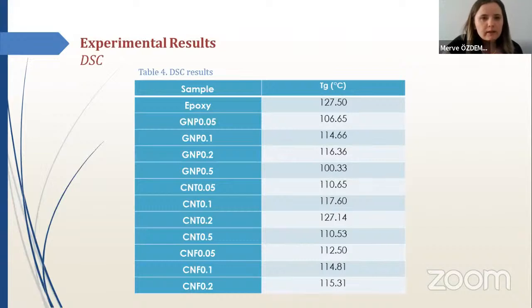Last one, DSC results. When the DSC results were examined, it was observed that the addition of GNP decreased the glass transition temperature of the resin. Similarly, the addition of CNF and CNT decreased the glass transition temperature of the resin.